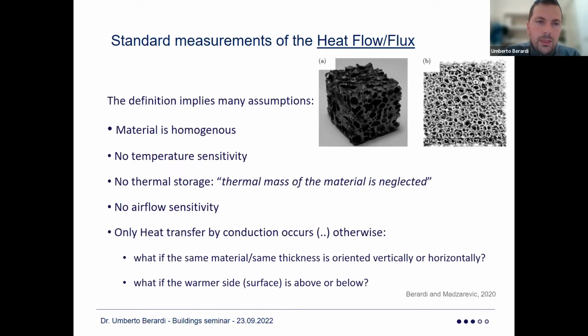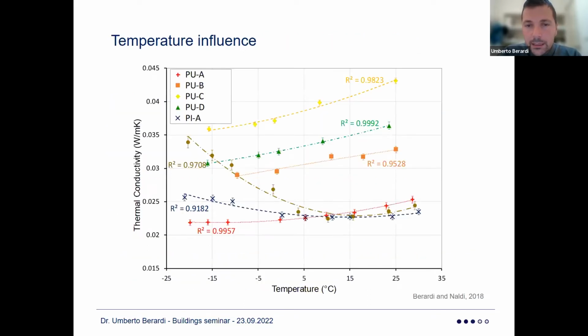But in brief, what we've been doing is trying to overcome the assumptions that typically are made in heat flow measurements. If you see the premises of most of the codes, standards and norms to look at thermal conductivity, you pretend the material is homogeneous, is not temperature sensitive, doesn't accumulate heat, doesn't get affected by airflow paths, and more importantly, only transfers heat by conduction. In reality, these materials do quite the opposite. They are affected by air, they're affected by moisture, they're affected by temperature.